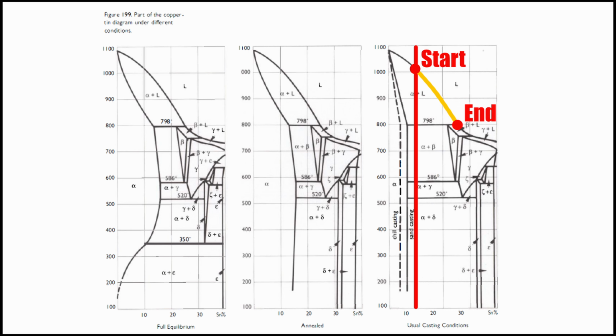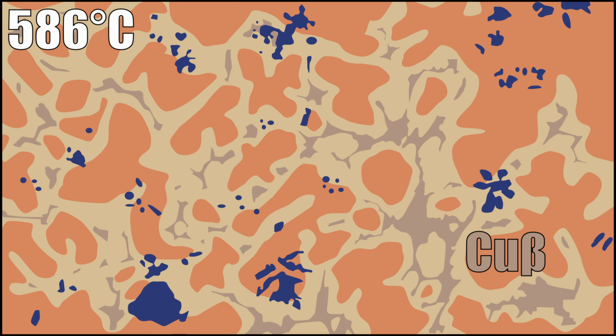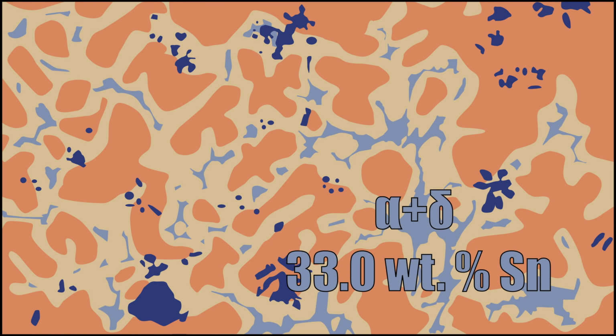We cross into the beta phase field during cooling. The last solid to form from the melt is the beta phase. From this point on, all reactions occur in the solid state, with no liquid present. The beta is no longer stable below 586 degrees, transforming into gamma phase and subsequently the delta phase, marking the end of the reactions.